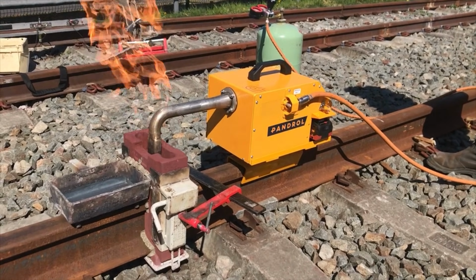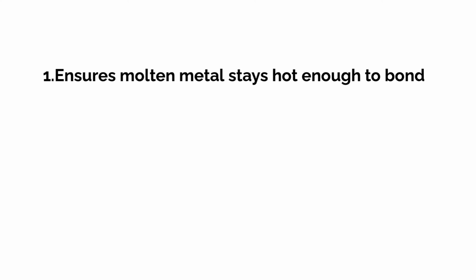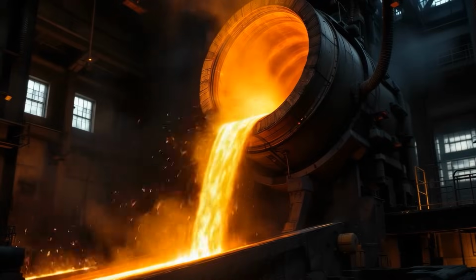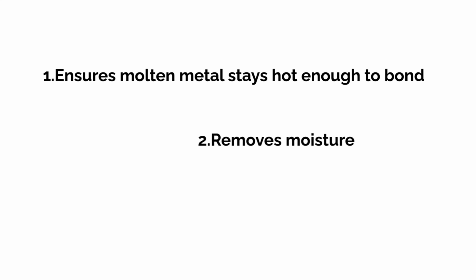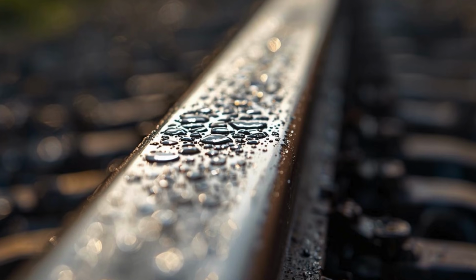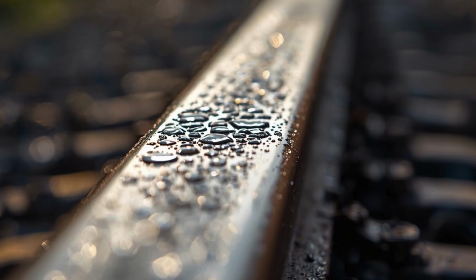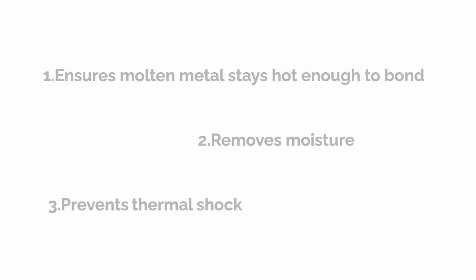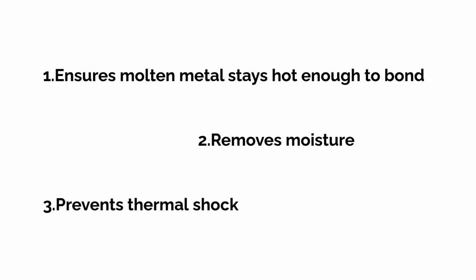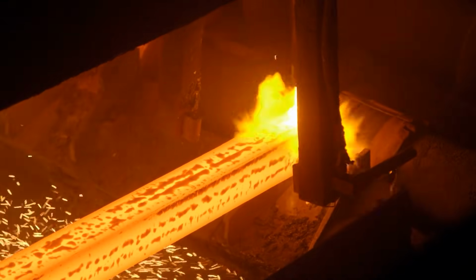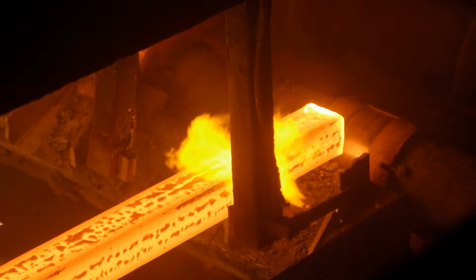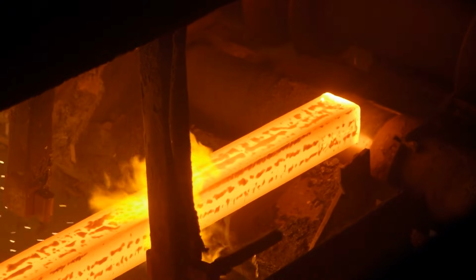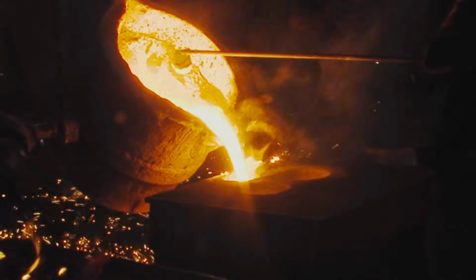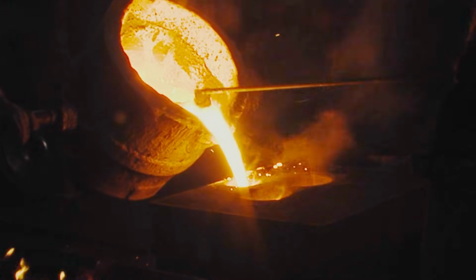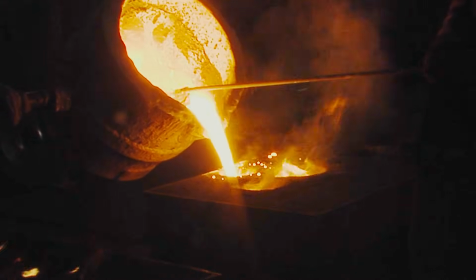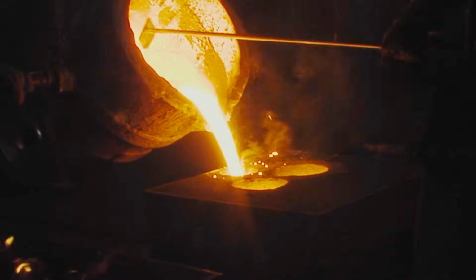This preheating does three key things. It ensures the molten metal stays hot enough to bond with the rail ends, rather than cooling too quickly and failing to fuse properly. It removes moisture, mostly from the mould material, but also from the rail surface if the weather's damp. This reduces hydrogen that could cause cracking, known as hydrogen-induced cracking. Then, it prevents thermal shock within the rail itself by equalizing the temperature across the rail's cross-section, avoiding the sudden expansion and contraction that can distort or fracture the heat-affected zone. Think of it like easing metal into the heat rather than shocking it, letting the atoms expand gradually so the bond that follows is solid from the start. If you skip this step, the hidden cracks or poor fusion almost guarantee the weld's early failure.